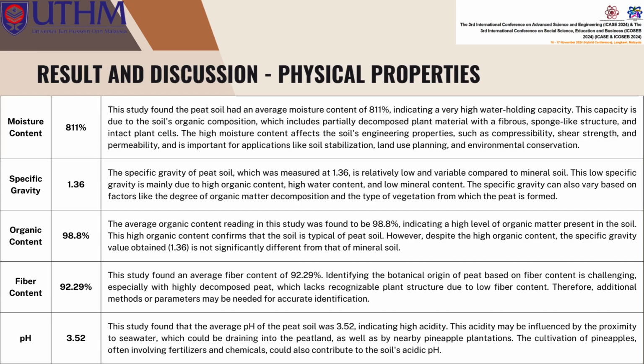This value can vary depending on the degree of organic matter decomposition and the type of vegetation that formed the peat. This study found that the soil had an average organic content of 98.8%, characteristic of peat soil. Despite the high organic content, the specific gravity value of 1.36 is not significantly different from that of mineral soil. This study also found an average fiber content of 92.29%. Identifying the botanical origin of peat based on fiber content is difficult, especially with highly decomposed peat lacking recognizable plant structure. Additional methods may be needed for accurate identification.